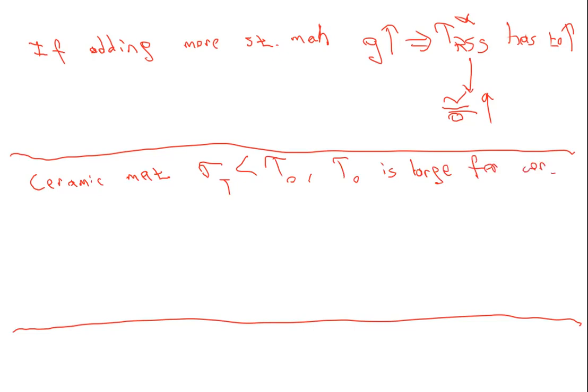Ceramic materials. So dislocation exists and moves only when you apply a lot of stress. And once you apply a lot of stress, you activate this dislocation, you are increasing your G, you're increasing your tau, resolved shear stress, then you need to increase your stress tensor, which makes the material more ductile. But in ceramics, since lattice resistance is too high and the stress tensor cannot exceed the lattice resistance, we see this material is brittle. If we cannot exit the barrier, then that's a problem.